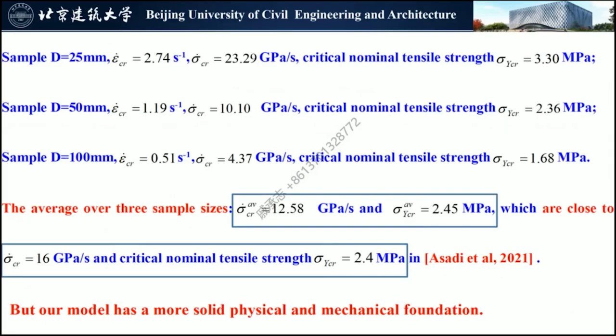For three kinds of rock samples with diameters of 25, 50, and 100 millimeters, we have calculated the critical strain rate and the critical nominal tensile strength, and the average over the three sample sizes. The obtained values are close to the values obtained by Asadi et al. But our model has a more solid physical and mechanical foundation.